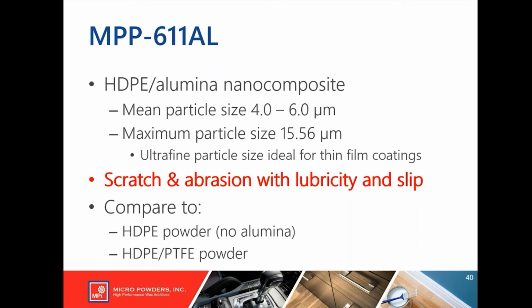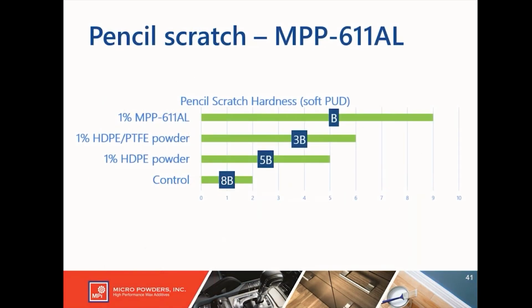So basically the same particle as this without the alumina, and we're going to compare it to a polyethylene PTFE composite powder. So here's that pencil scratch results. This is a soft PUD in this example, so the control has a pencil scratch rating of 8B. 1% high-density polyethylene improves that to a 5B. 1% of the high-density polyethylene PTFE powder improves that still to a 3B.